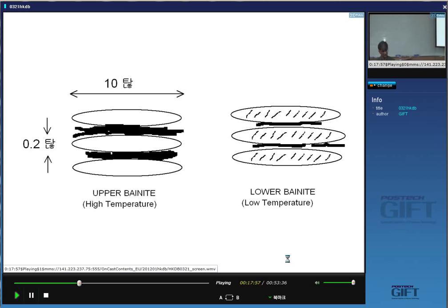And whatever theory you have, you've got to be able to explain this. Okay? You've got to be able to explain this quantitatively. When will we get lower bainite? When will we get upper bainite? And why is it important? This is a very bad microstructure, because here we are not tempering, we are not controlling the precipitation of cementite. The cementite actually forms during the course of transformation. So they tend to be very big particles of cementite, and that ruins the toughness if you are working on